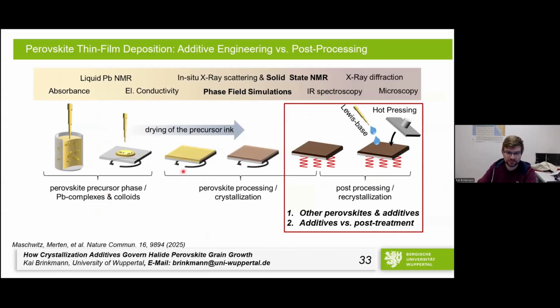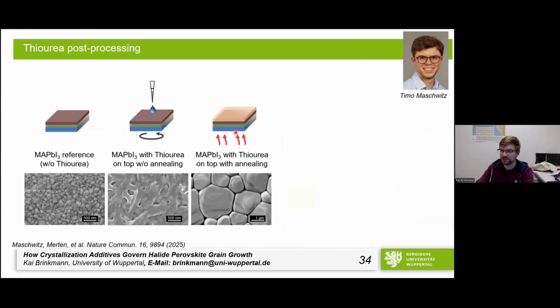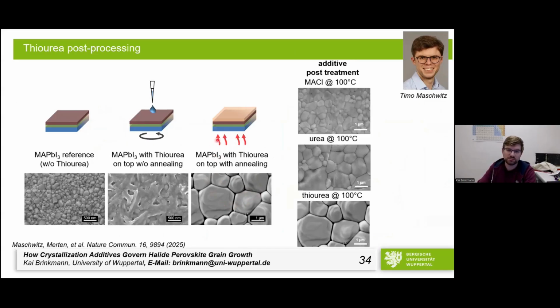Finally, other perovskites, other additives. Now we're talking about post-processing. One thing that we did is, if we have a perovskite and if we can reform it with additives, we can just spin coat it on top, right? And it actually works. So you can just dissolve the thiourea in isopropanol, spin coat it on top, put it on a hot plate, get large grains. And the trend follows perfectly what we just learned in DFT. So methyl ammonium chloride gives less mobility, urea is the next, then thiourea.